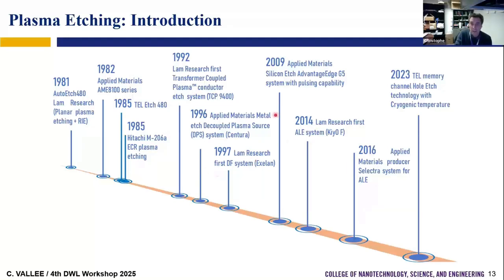In the 90s, that is when we started to introduce HDP sources, like the inductively coupled plasma system. And at the end of the 90s is where we started to introduce the dual frequency plasma etching process. After that, we started to introduce pulsing capability, pulsing the plasma, pulsing everything, like atomic layer etching systems. And the latest generation of plasma etching reactor uses cryogenic etching.